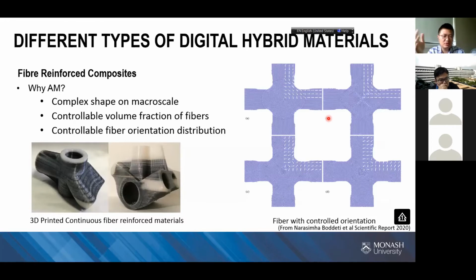The first thing is that, compared to the conventional fiber reinforced composite fabrication process, additive manufacturing can help us fabricate parts with really complex shapes on the macroscale. Second, we can control the volume fraction of the fibers, and also the fiber orientation. Conventionally, in fiber reinforced composite fabrication, each layer can have only uniform fiber orientation, 0, 90, 45. We can only have certain angles, with all fibers oriented at those angles, and the same fiber volume fraction everywhere. But with additive manufacturing, we have more freedom. We can digitally control the fabrication process using the toolpath and achieve different fiber orientations in the structure, which can further improve the mechanical performance of the part. I will show you another example later in my slides of how to achieve this type of design.